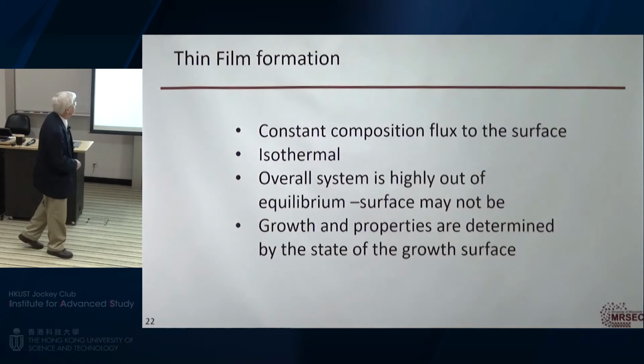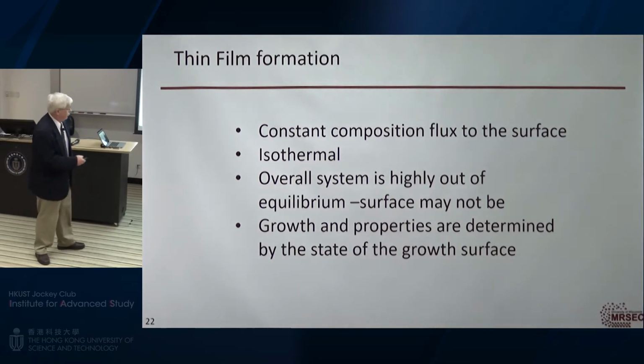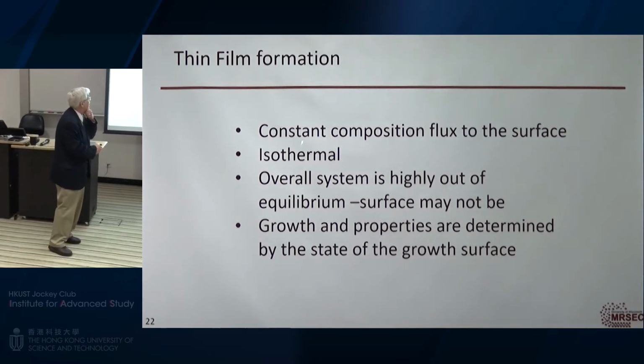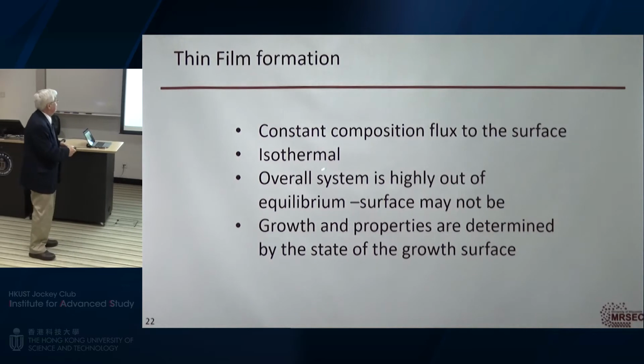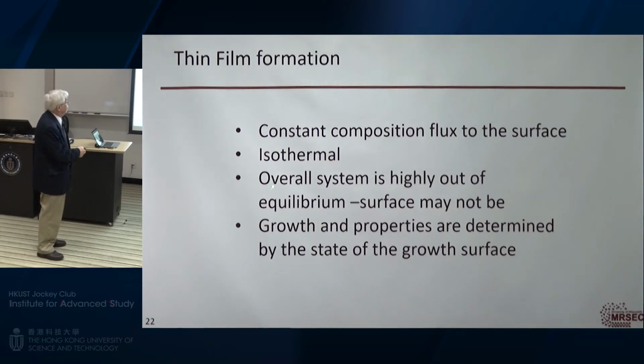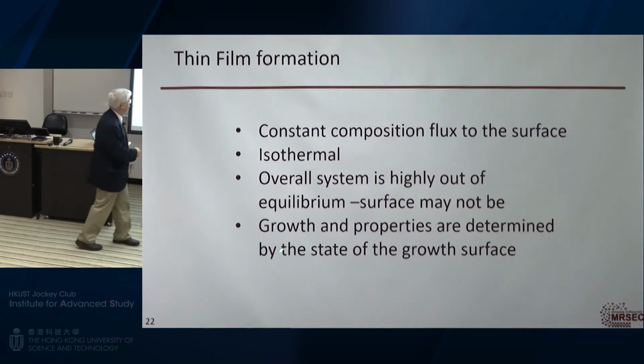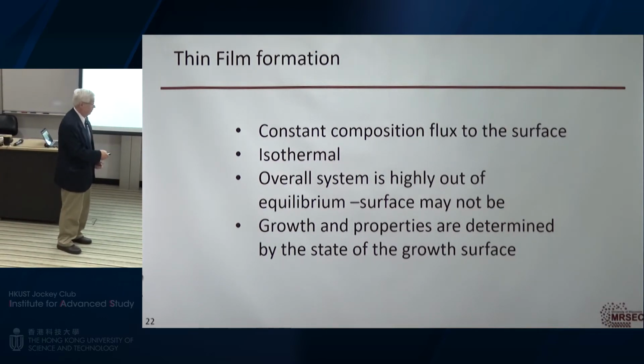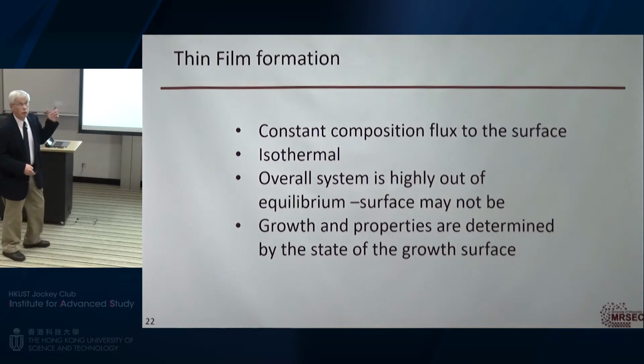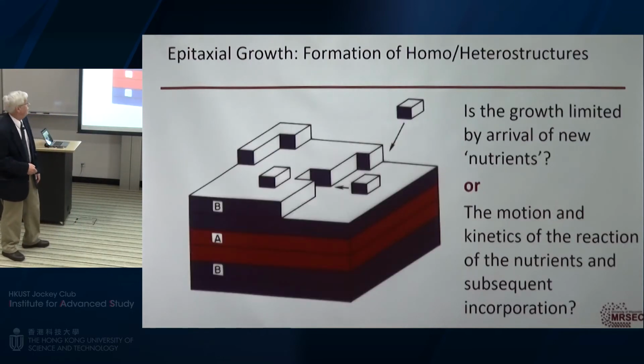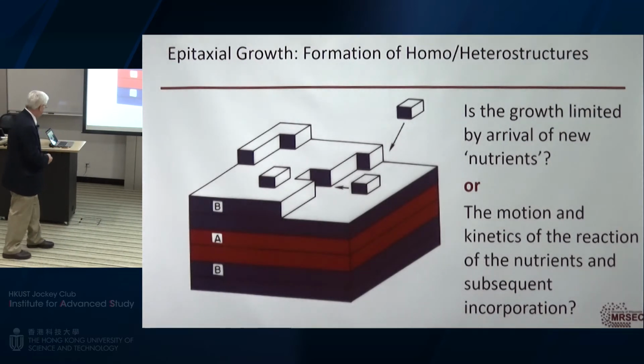And the reason we use thin film formation is because I can have a constant compositional flux to the surface. It's not like I'm growing a crystal out of a constant volume, which was the pot of molten silicon. And overall, it's an isothermal system typically. The overall system is highly out of equilibrium, but the surface may not be. And we'll show that. And the growth and properties are determined by the state of the growth surface. And this is going to be a recurring theme. What happens at the growth front is actually going to determine whether we can make some of these materials we can design. So epitaxial growth, or thin film formation,